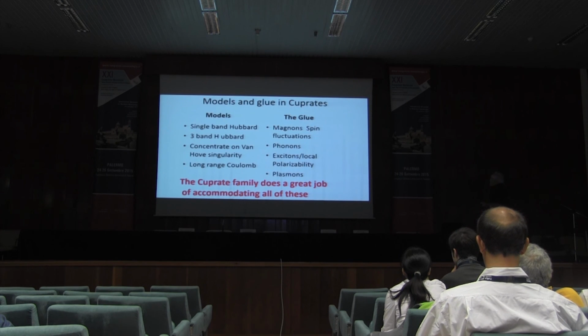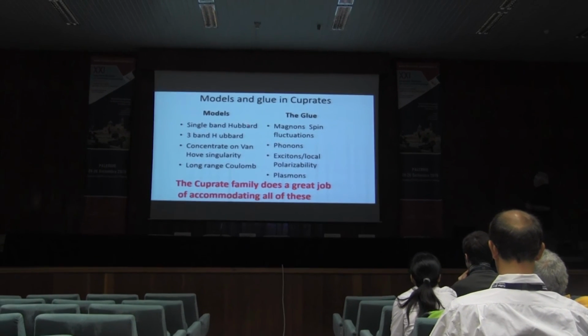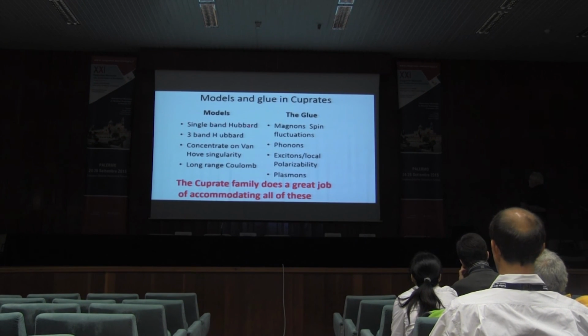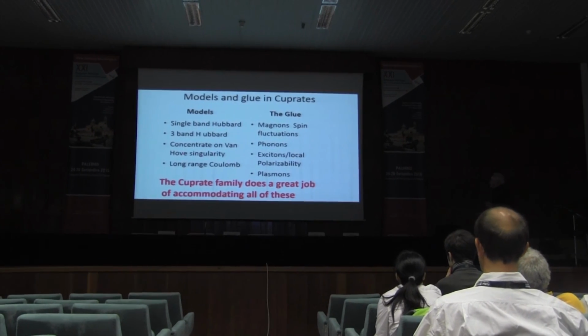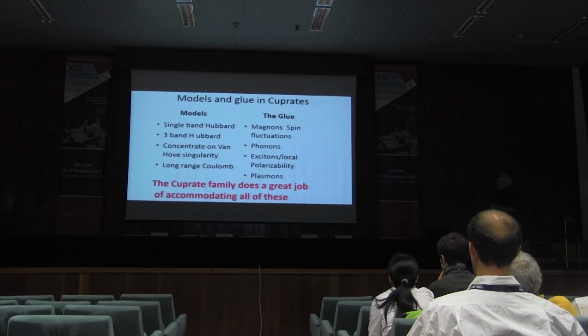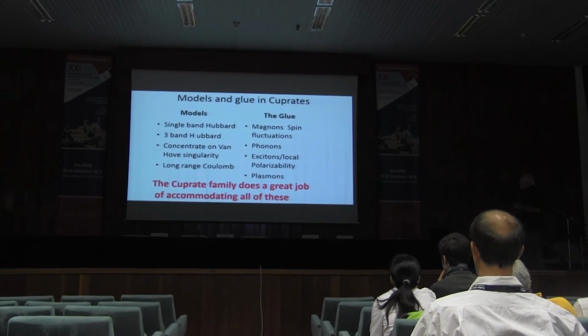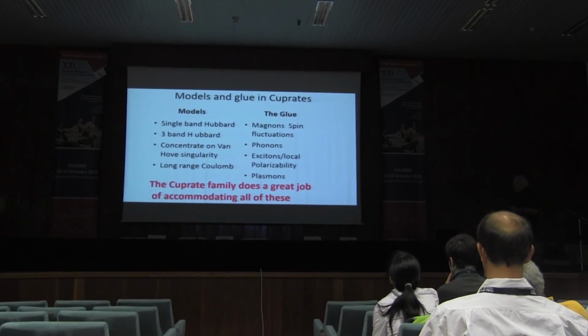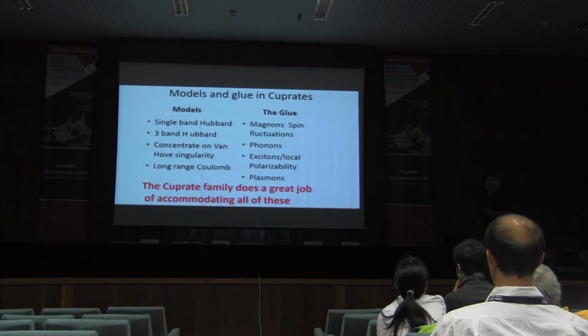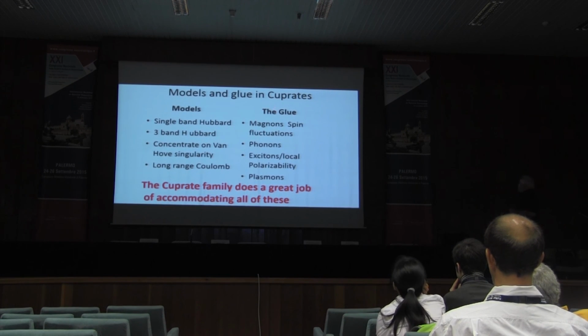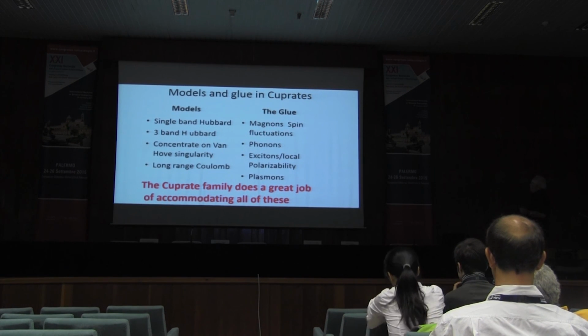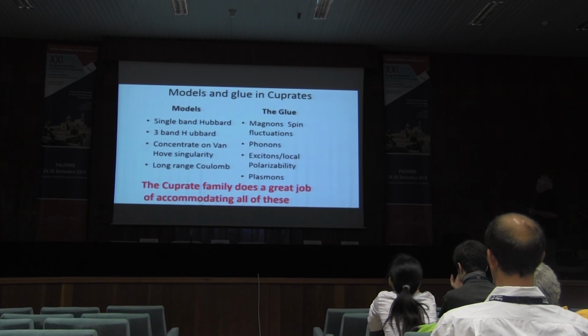And for the cuprates, for example, the models and the glue in the cuprates, well, we have models. There are single-band Hubbard models. You have three-band Hubbard models. You have models which concentrate on the importance of the van Hove singularities. And we have models like Tony Leggett's that concentrate on long-range Coulomb interactions rather than the Hubbard short-range ones. The glues that people talk about are magnons or spin fluctuations, phonons.